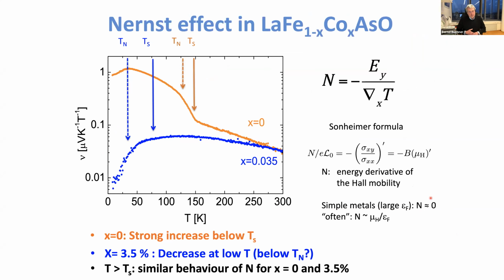The Nernst effect is even more complicated in some sense, because in simple metals, the Nernst effect is always zero. Some of you might remember all the discussions on the cuprates on the reason of the Nernst effect, which I will not solve. So the Nernst effect is the energy derivative of the Hall mobility. And here you see the parent compound and the doped compound, very much different in the ordered phases, but at high temperatures rather similar.